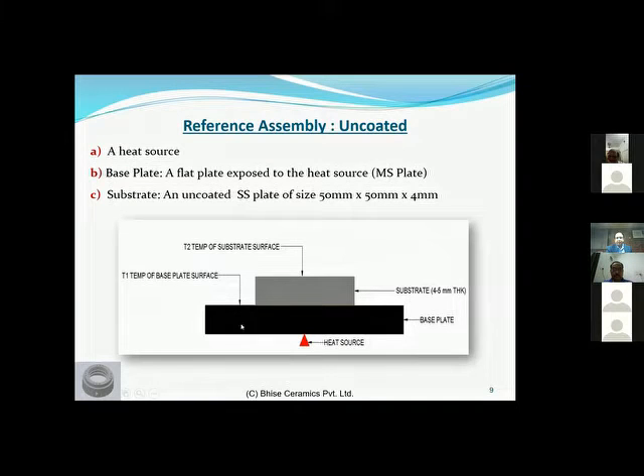You have a base plate, which is a MS plate, and you have a substrate on top. The base plate is made of MS. We have taken a base plate over here so that the heat source heats the base plate. We have the hot face reading. This is the temperature of the base plate, which is the hot face reading. And you have the temperature of the top of the substrate, which works as your cold face reading.